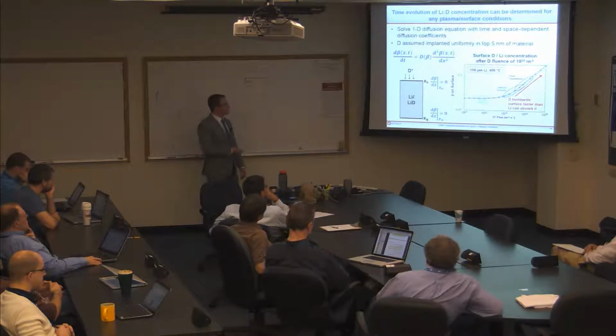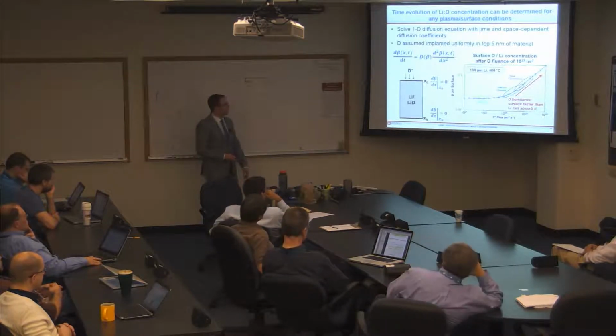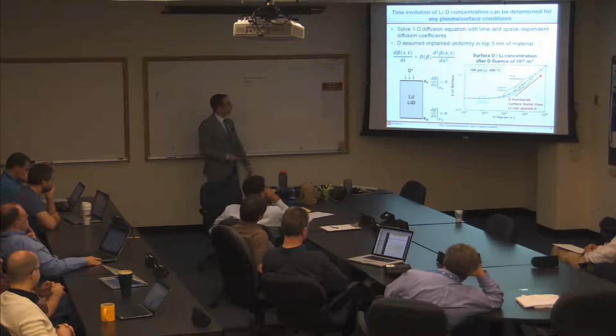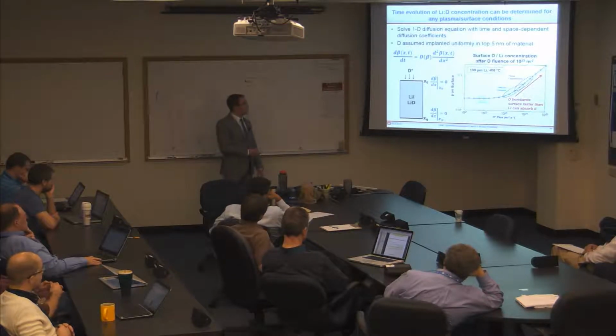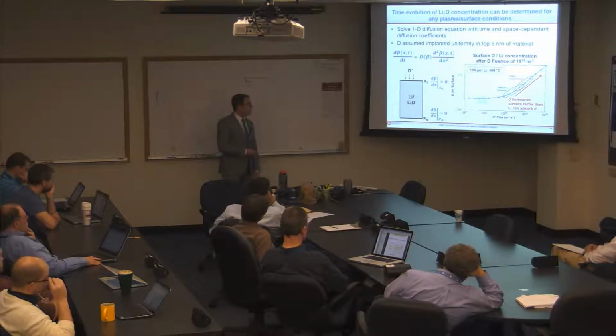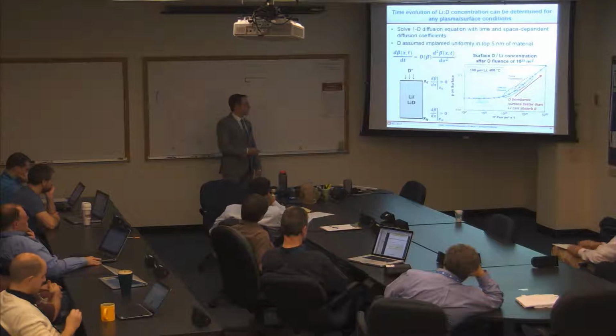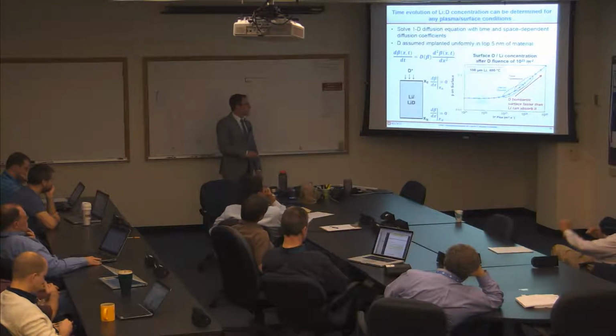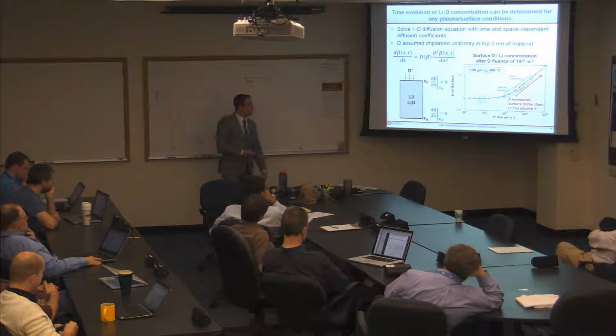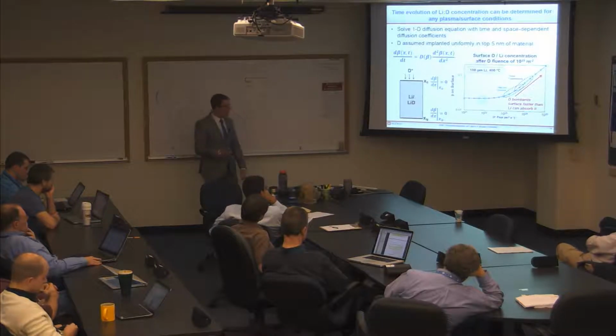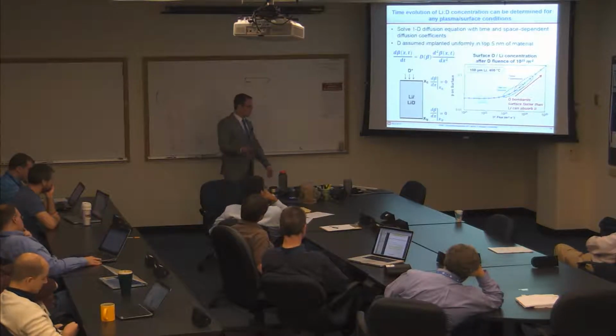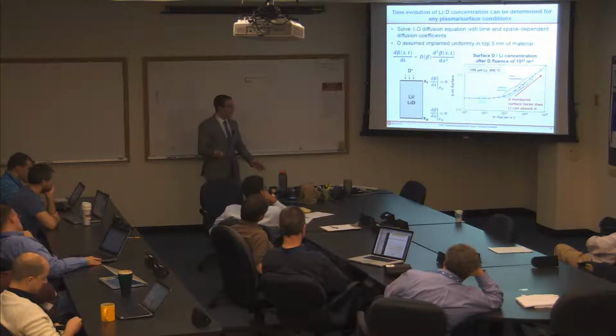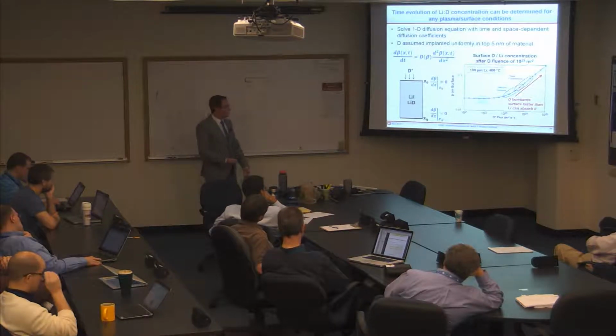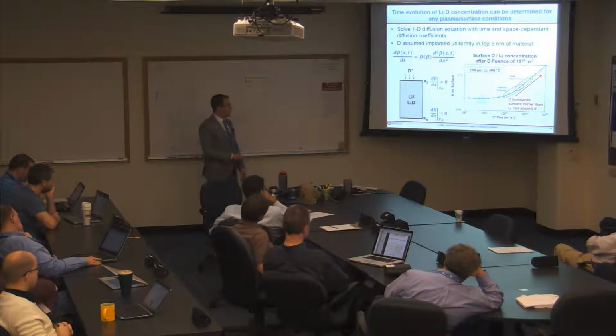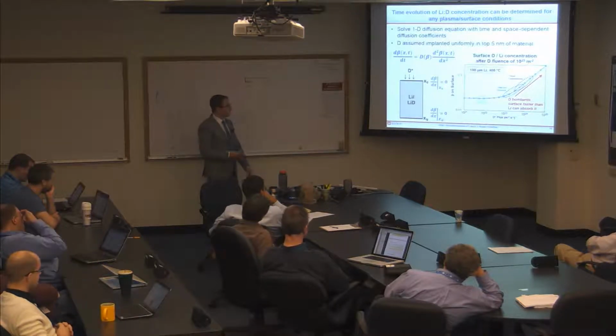So you can just do this in 1D with a 1D diffusion equation, Fick's law, which is given right here. For our purposes, I just assume the deuterium is implanted uniformly in the top 5 nanometers, and then you establish the boundary conditions that the deuterium can't diffuse back out into the plasma or into the substrate underneath. And what we are interested in is if you expose the lithium layer to some constant fluence of deuterium atoms, but at varying fluxes, how does the concentration of deuterium atoms beta on the surface change as a function